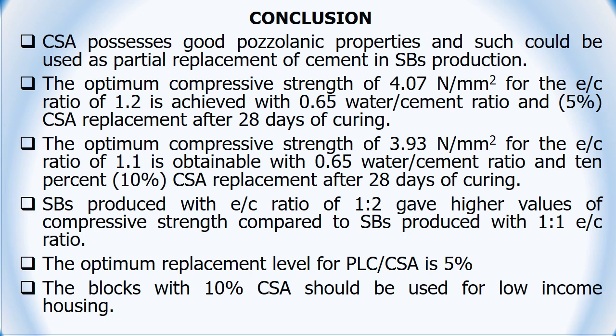Conclusion. From the laboratory analysis and the results obtained, the following conclusions are drawn. Coconut shell ash possesses good pozzolanic property and as such could be used as partial replacement of cement in sandcrete block production. The optimum compressive strength of 4.07 Newton per millimeter squared for the e/c ratio of 1:2 is achieved with 0.65 water cement ratio and 5% coconut shell ash replacement after 28 days of curing.